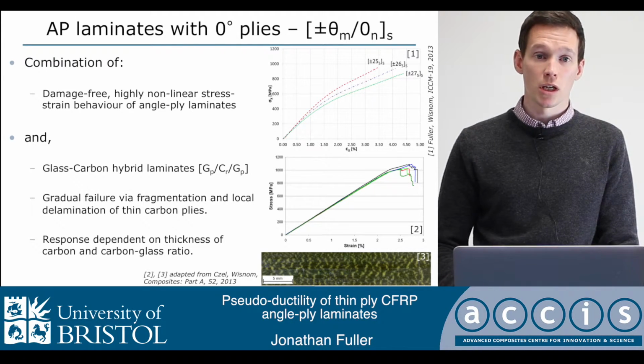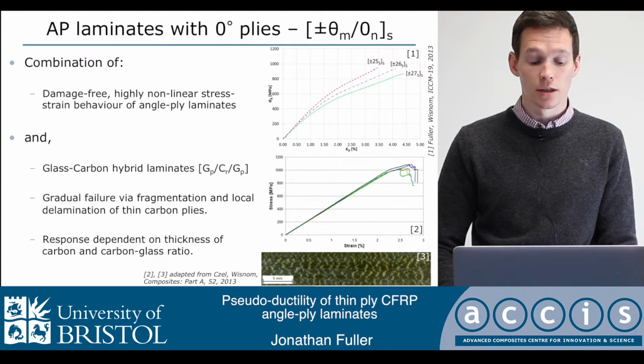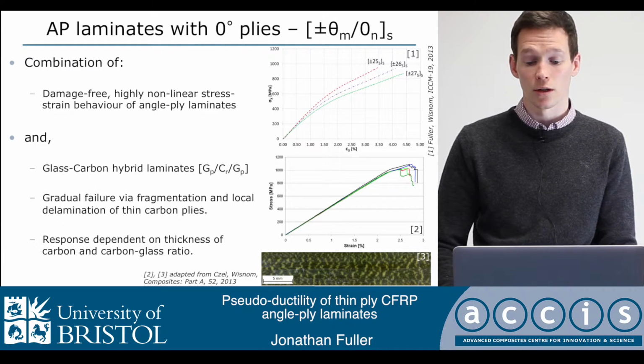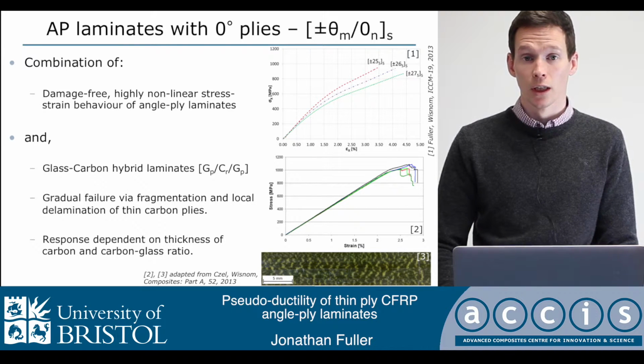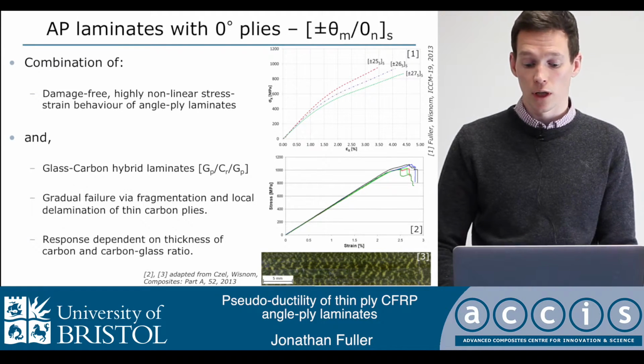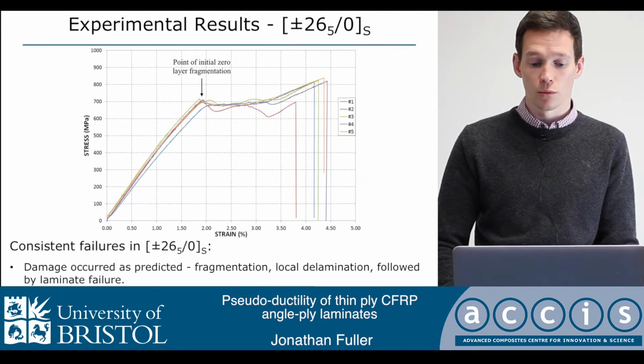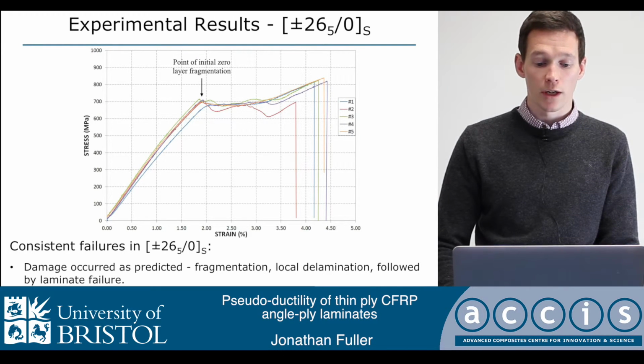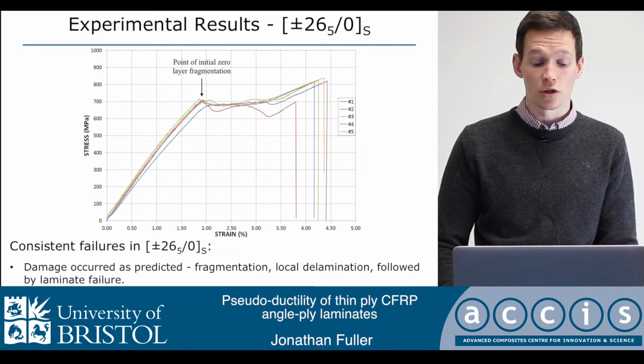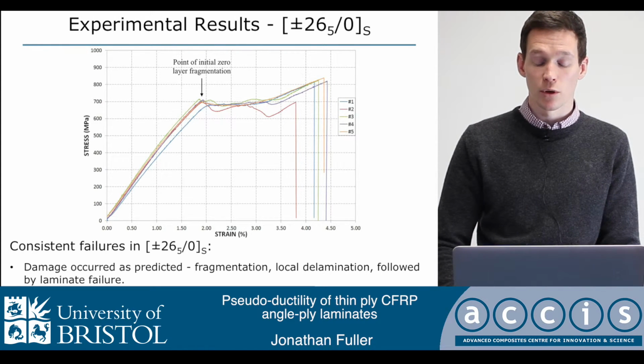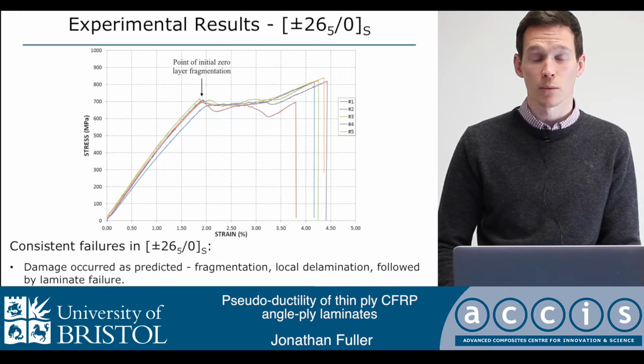Now, this behavior can be adjusted or tailored depending on the ratio and the absolute thickness of the carbon and glass ratio. So it gives great control over the behavior and the stress strain curve that we can produce. So coupling these two, we get a response very much like the one shown here, a metal-like stress strain curve with an initial largely linear loading up to about 2%, and then a plateau at 700 megapascals up to in excess of 800 megapascal strength after further loading.